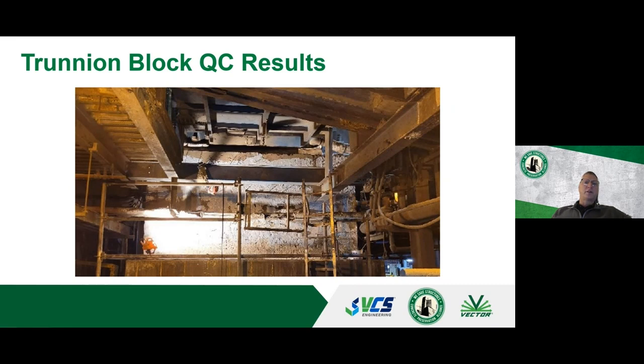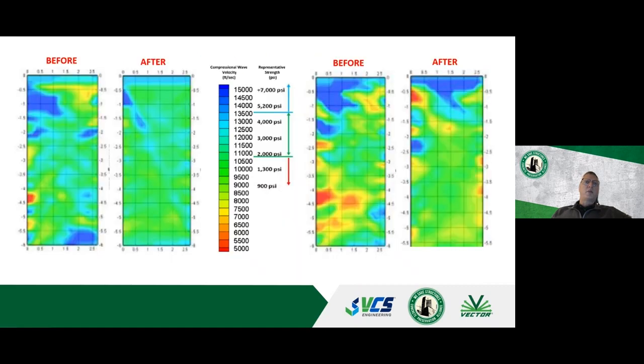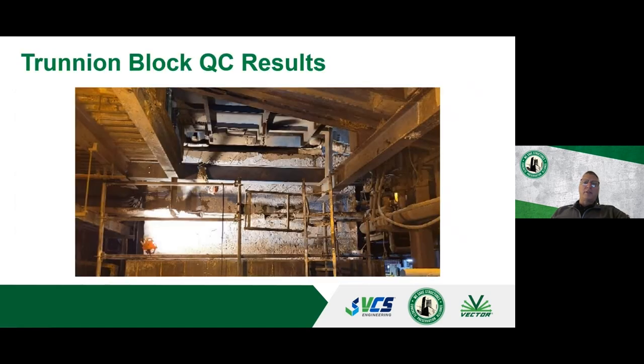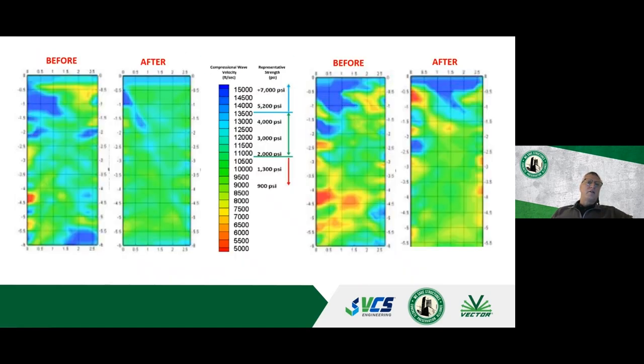There's a large motor, and a trunnion on top of it, a bearing block. We needed to verify while on site that everything had been fixed. So we did impact echo before, and we did it after. You can see there's a lot of material in the way, so you can't get to every single inch of it, but you could see that the darker the color, the closer to red it is, the lower the PSI.